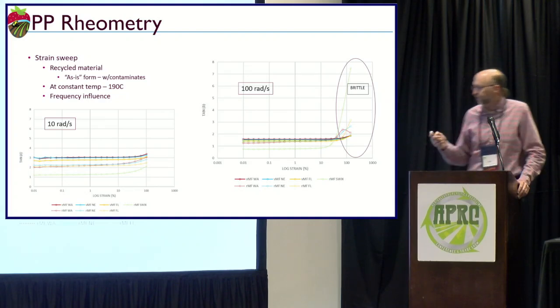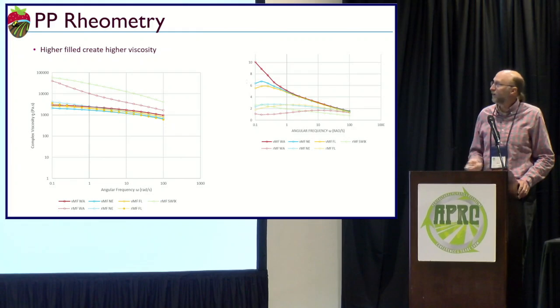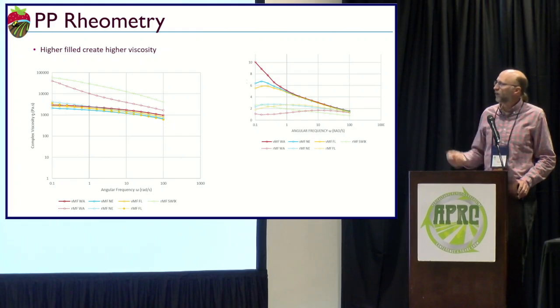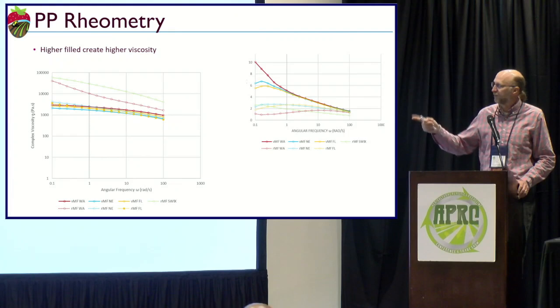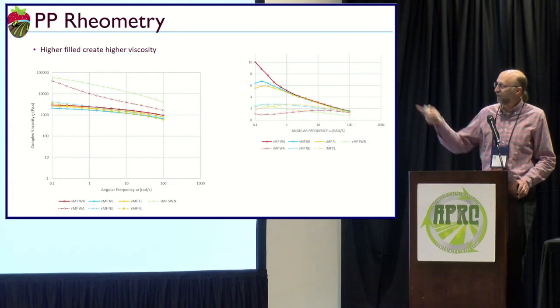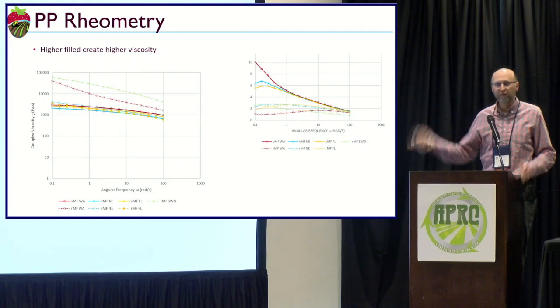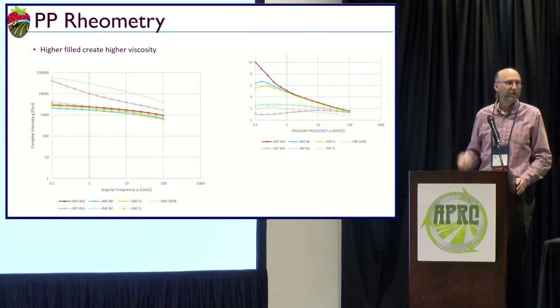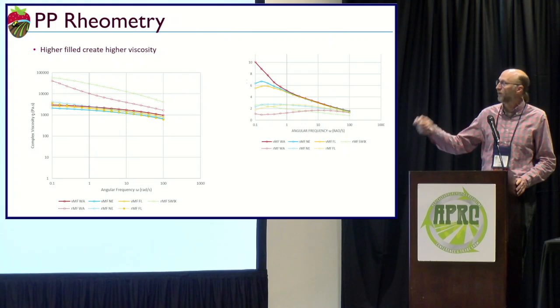And so what we want to do next, well, this is another parallel plate rheometry kind of thing that I'll go into, but it's also showing angular frequency. It's also looking at this as a viscosity measurement here. So the higher the filler, the higher the viscosity is going to be. And you can see the Swix material, once again, is pretty high.